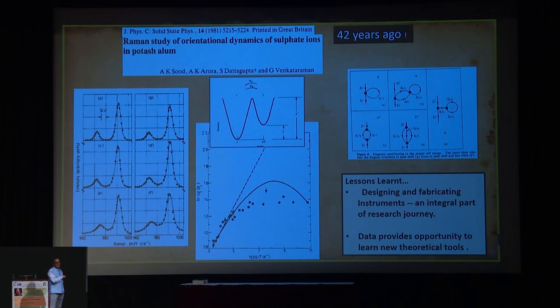And this is a very early experiment, 42 years back, we published, on potash alum, which is potassium aluminium sulfate, and look at the Raman spectrum. And these two lines are the vibrational modes of a sulfate ion, because the sulfate ions are in two inequivalent crystallographic orientations. And the area ratio between them as a function of temperature did not follow the Arrhenius law. That was thankful, because if it was Arrhenius, it would have been boring physics.